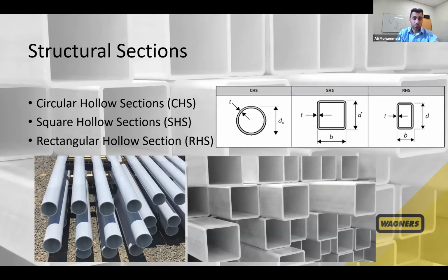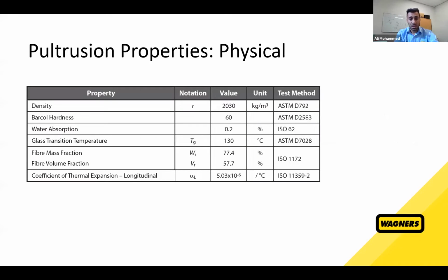As I mentioned earlier about the pull winding process, it will result in better physical properties, as we can see in this slide, which presents the physical properties of Wagner's pultrusion. The main thing to look at here is the fiber mass fraction and fiber volume fraction, which is nearly 80% and 60% respectively, one of the highest fiber contents of the current pultrusion in the world. So with this high fiber content, plus the quality of the fibers and the resin mixes